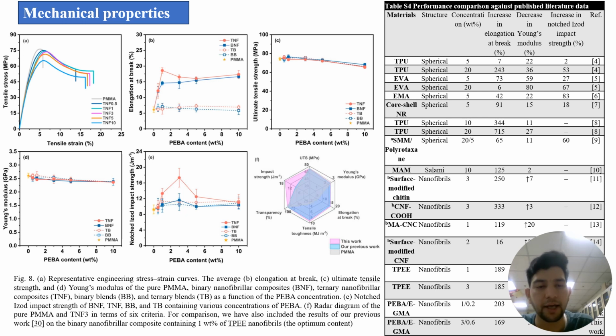Only this one shows a good result in the radar in figure 8F and table S4. So this shows a comparison with previous data. In the radar diagram, TNF3, containing 3% PEBA nanofibers and 0.6 weight% EGMA, significantly improves elongation at break. How much? 169, as you can see from the table for this work. And impact strength is 87% higher compared to PMMA. Tensile strength, stiffness, transparency and performance comparison against published literature data are presented in the table and the remaining data shown in the paper.